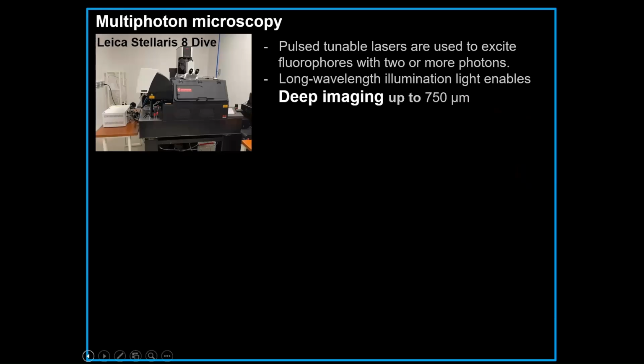This Leica Stellaris 8 microscope has another capability called multi-photon microscopy. So this microscope is equipped with pulsed tunable lasers, and pulsed lasers are used to excite fluorophores with 2 or more photons. And usually we use infrared light wavelengths to illuminate the sample. Those longer wavelength lights can penetrate tissues and samples deeper. So it is used for deep imaging up to 750 microns. Previously, I showed you the confocal 3D reconstruction. It was up to 250 microns. So multi-photon can go deeper.